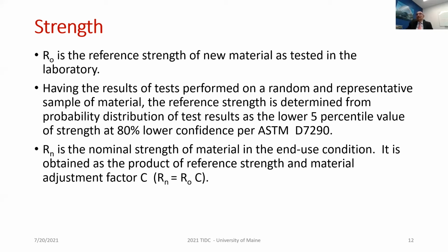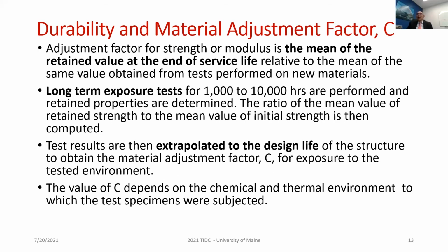As I said before, it's the product of the material adjustment factor that accounts for durability and the reference strength. How do we get the material adjustment factor, which is the basis of durability? We expose the material to different environments for a long period of time, between 1,000 and 10,000 hours. And then after exposure, we measure the properties such as strength or modulus, and take the mean of that and compare it with the mean of the new material that has not been exposed. And then extrapolate the results to the expected life of the structure. And this way we establish the factor C, from which the nominal strength is calculated using the reference strength.